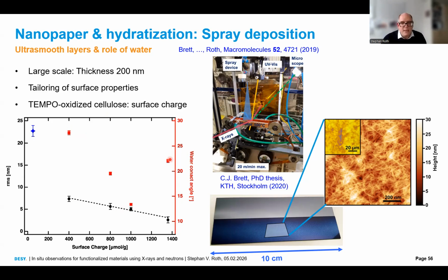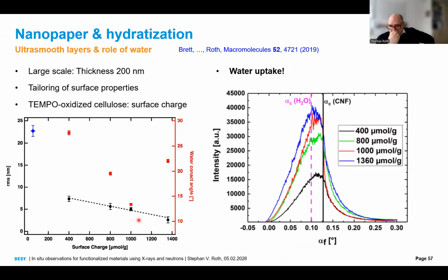And you see here that we have a sweet spot around 1000 micromole per gram surface charge of the cellulose nanofibrils, where the water contact angle is low, and we can expect a good imbibition if we use water-based materials. And the first question is, where's the water going? Everyone can do it in the morning. You take coffee and you let it drop on your napkin, and you see how the coffee and the water imbibes into this napkin. This is the water uptake.